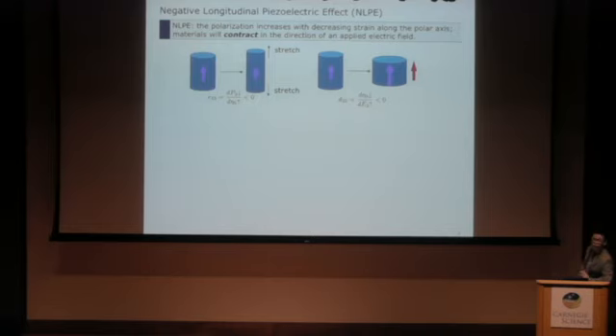And this is a very counterintuitive phenomenon because, based on the definition, when we stretch the material, increasing the strain, the polarization actually becomes smaller. So equivalently, when we turn on an electric field along the polar direction, even though the polarization becomes larger, the lattice constant becomes smaller, giving you a negative d33. So this is very counterintuitive.